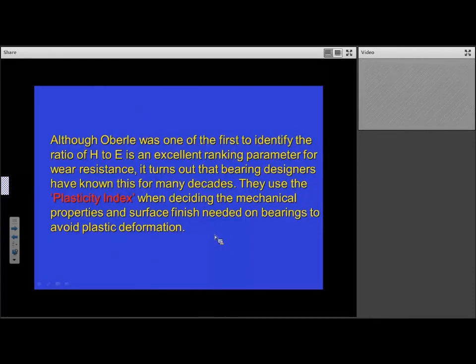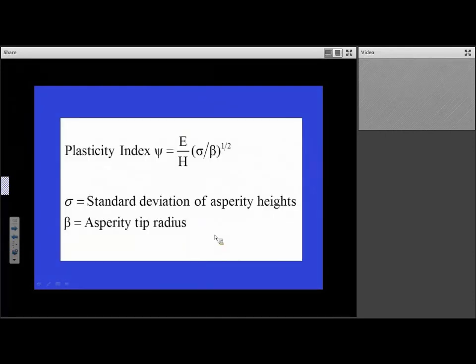So although Oberle was the first to identify the ratio of hardness to elastic modulus as an excellent ranking parameter for wear resistance, it turns out that bearing designers have known it for many decades, and they use something called the plasticity index when deciding the mechanical properties and the surface finish needed on bearings. So they use this plasticity index, which you'll notice has an E/H ratio in it, and it also has another factor related to surface roughness. So the bearing designers really thought that they had little control over this parameter, and therefore if they wanted to prevent a rough surface from exhibiting any plastic deformation, then they'd have to polish it to a very high level to avoid any plastic deformation of asperities.